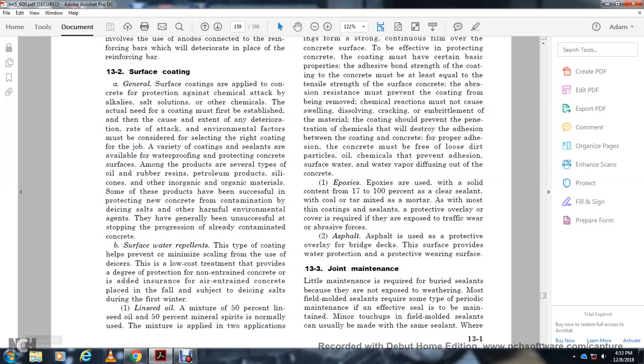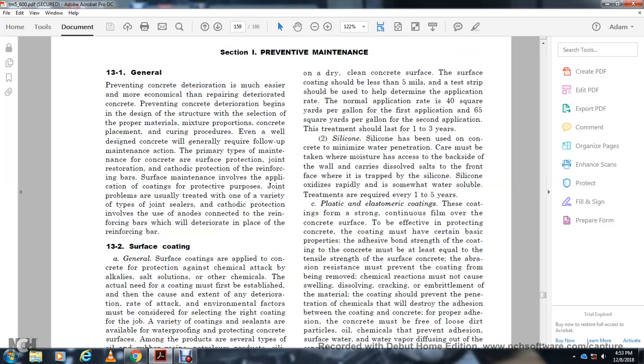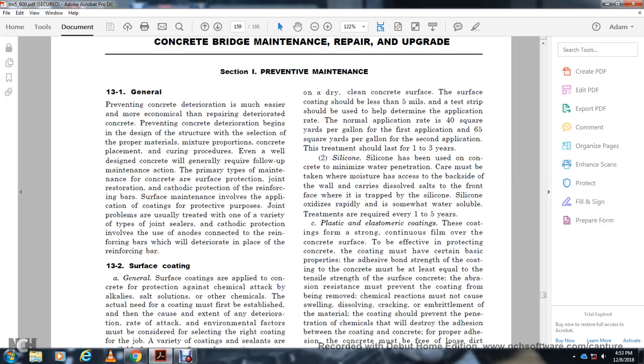Alright, linseed oil: a mixture of 50% linseed oil with 50% mineral spirits. Normal use is two applications on a dry, clean concrete surface. The surface coating should be less than 5 mils. A test strip should be used to help determine the application rate. The normal application rate is 40 square yards per gallon. The second application is 65 yards per gallon. The second application of the treatment should last 1 to 3 years.